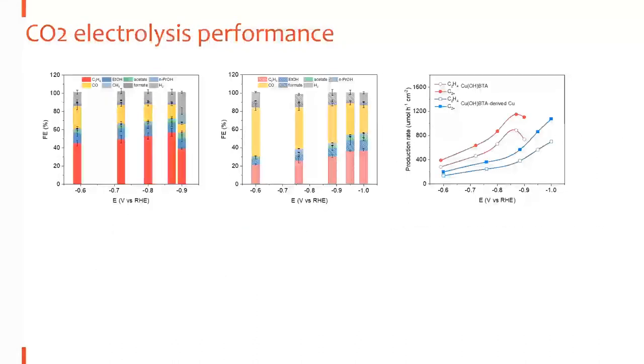So someone asked us about the performance. That means now you already have copper. Why do you need to have a new catalyst to study? So the reason is that we pursue better performance for C2 product. So if we compare our catalyst, copper BTA, to the copper nanoparticle control, we can see more straightforwardly that the production rate for C2 products, including ethylene, actually doubles the production rate of copper nanoparticles.